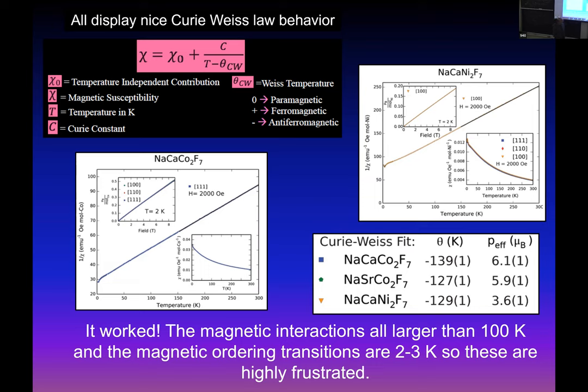So basically what the theorist asked me to do is to make something where this number was more than one. So now I have 129. So that's pretty good. The good news is that it made that. The bad news is that cobalt in this thing is spin 3/2. So you can see why I like cobalt so much for a minute.